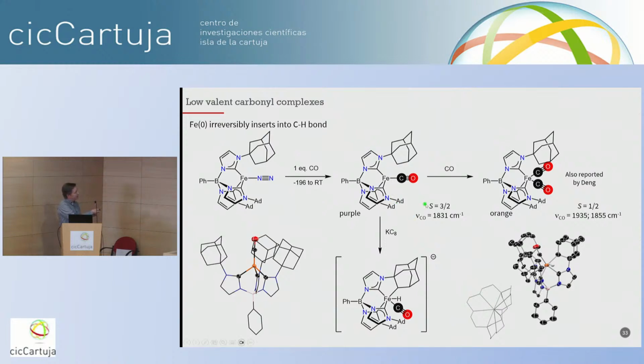So we can make a monocarbonyl complex if we're very careful about controlling the stoichiometry of the reaction with CO. And if you add too much CO, you make the dicarbonyl. But if we try to reduce this, what happens is that we actually get insertion into the CH bond of the adamantyl, make this diamagnetic compound. This is an irreversible reaction. So this is not going to be the way to do it.